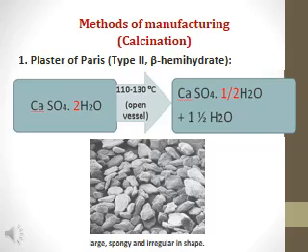By this way, we can obtain calcium sulfate hemihydrate plus 1.5 molecule of water. So by heating this way, 1.5 molecule of water is extracted from the calcium sulfate dihydrate to obtain calcium sulfate hemihydrate, which is type 2 or beta hemihydrate or plaster of Paris. Okay, these powder particles, because of this primitive technique, are irregular and large and porous, highly porous.